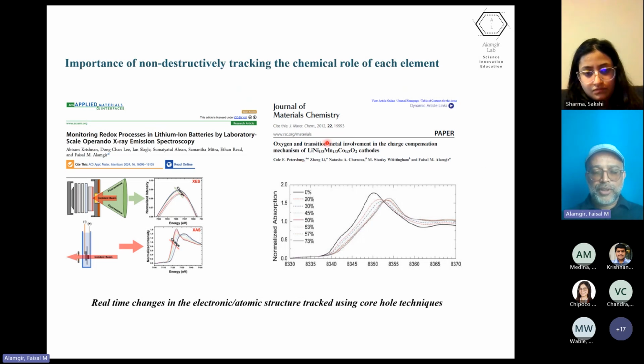My group is not the only group that has been doing this. This has been done by many others, but not at the lab scale, but at external facilities. And at these external centralized facilities, such as synchrotron facilities, a lot of this kind of work has been done in the past. This is just an example from my group in the past, and that was with the so-called nickel manganese cobalt oxide based cathode materials, or NMC.